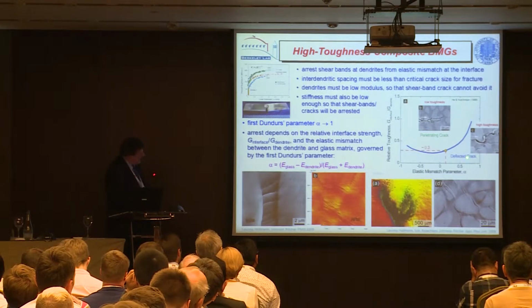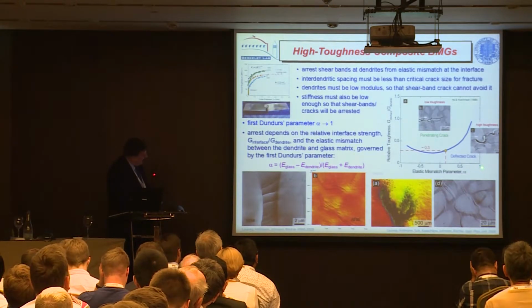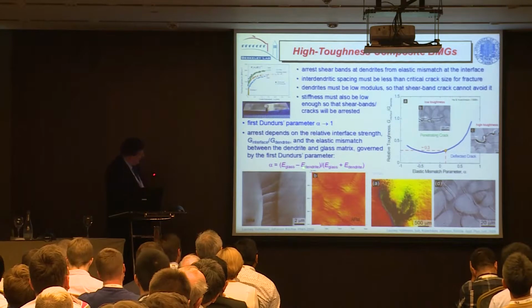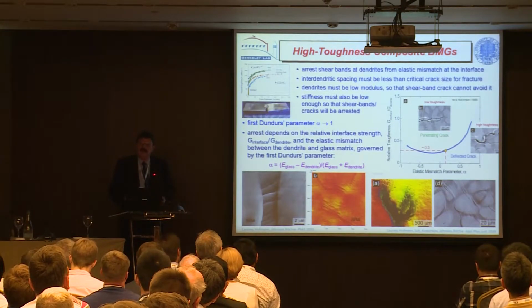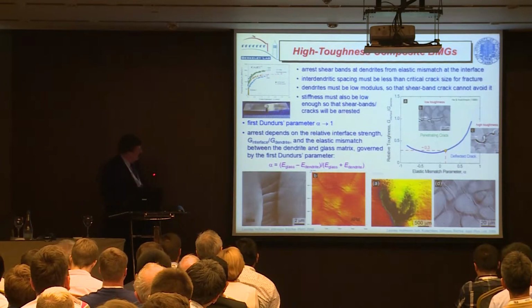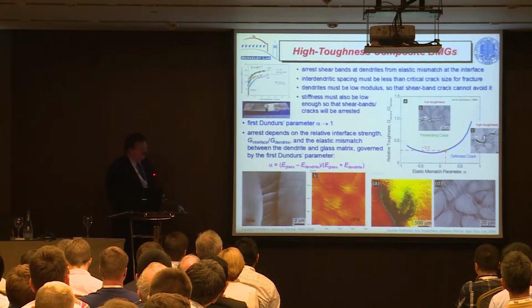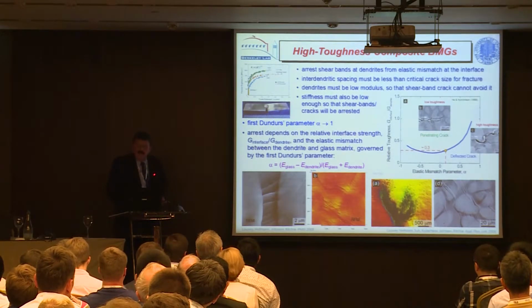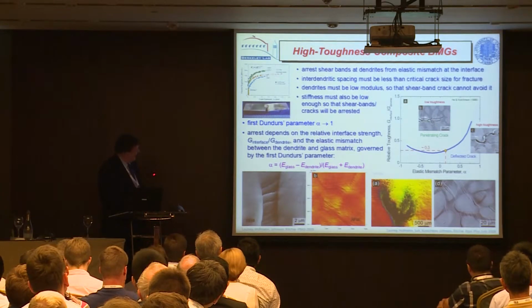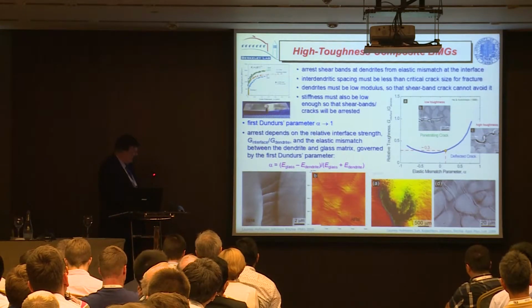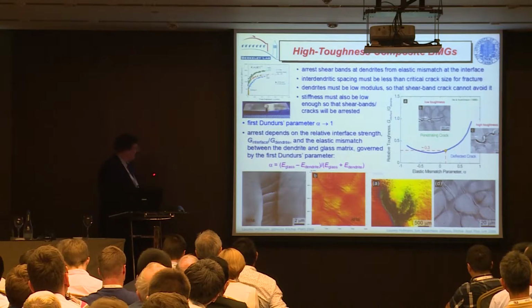And so to get in this region, you want the Dundurs parameter to be close to 1, so you want the stiffness of the second phase to be as low as possible. And this made very good materials, and in fact they're being used by NASA a lot now. The guy who did a lot of the work was Doug Hofmann, who of course works with NASA.